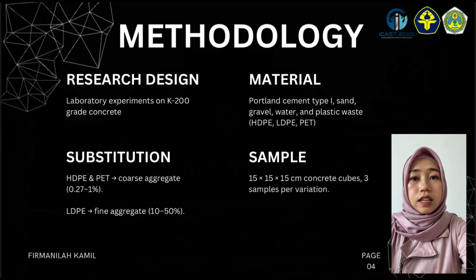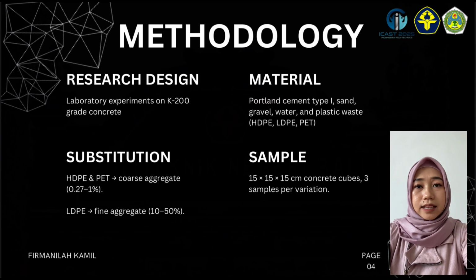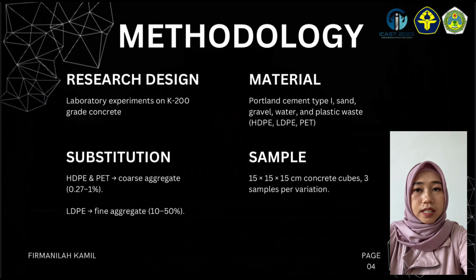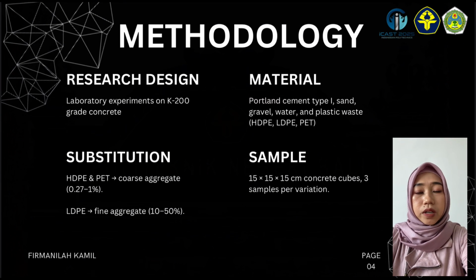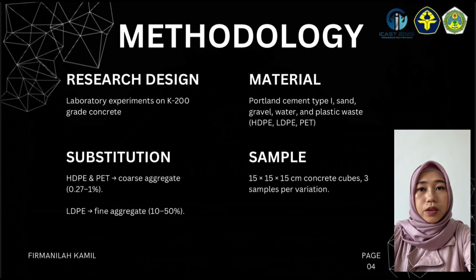Allow me to explain the methodology of our research. This study was conducted through laboratory experiment using K200 grade concrete as the base material. We used several types of plastic waste as substitution materials. HDPE and PET were applied as coarse aggregate substitutes in the range of 0.27 to 1%. LDPE was applied as a fine aggregate substitute with substitution level from 10 up to 50%.